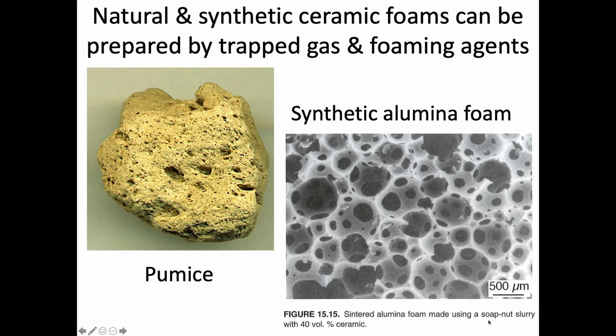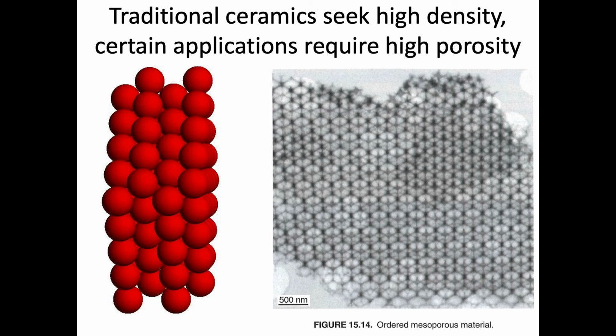This one is with what's called a soap nut slurry, and that basically has a foaming agent that would create gases that end up getting trapped in the structure. You can also, I'm going to go back to the previous slide, you can also add things. So this is an example where we have some type of bead, like a polymer bead that's available, and we put that in a very ordered structure or disordered structure, whatever we want, and then we put a slurry of the ceramic around it. When those beads are heated up, they decompose and leave behind porosity. In this case, we can have a very ordered structure, but it's very porous. So that's another way we can do it. We can add things like beads or other decomposing materials to create porosity as well.